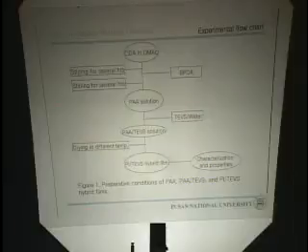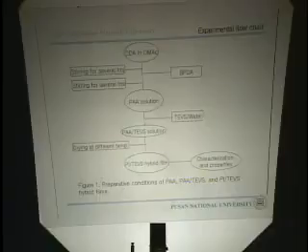Let me talk about figure 1, which indicates the preparation conditions of polyamic acid, hybrid solution and hybrid composite film. First we dissolve ODA in DMAc, then stir for several hours. After getting a complete solution, we add BPDA and stir again for several hours to get a homogeneous solution. Then we got this PAA solution, and we add polysesquioxane with different amounts as per our need. Then this is the hybrid solution, which is dried at different imidization temperatures to give the hybrid film, followed by characterization and properties. That was figure 1.